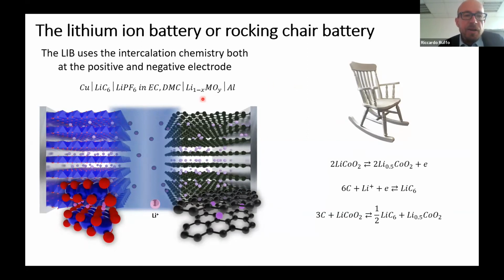In this device, we have a layered oxide on the positive electrode and graphite on the negative electrode. During the first charge, I remove the lithium from the layered oxide and I put the lithium into the graphite. So basically, my real cathodic and anodic materials are the delithiated layered oxide and the lithiated graphite, and when I need energy, I can just put an external load on the two terminals, and I have the spontaneous flow of energy through my system thanks to the spontaneous delithiation of graphite and lithiation of the delithiated transition metal oxide.